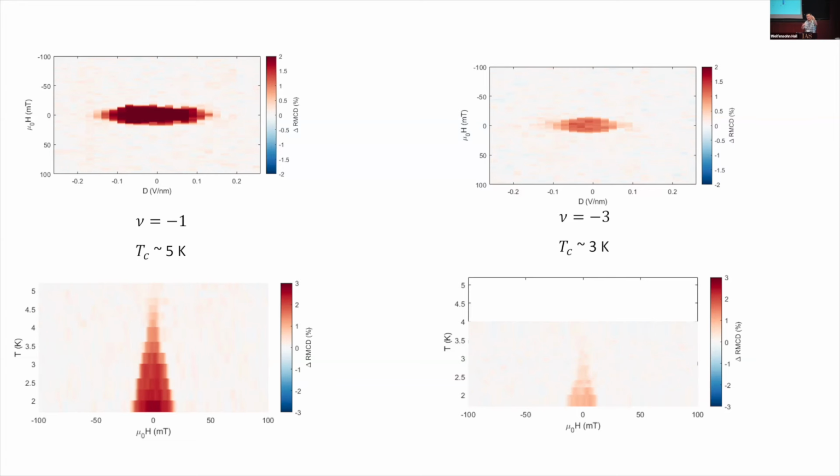When you reduce the twist angle, it means you enlarge the moiré size. Then the absolute carrier density, or you can think of the separation between the carriers in moiré orbitals, becomes larger and larger. Therefore the exchange interaction becomes smaller for smaller twist angles. That's the reason why the Curie temperature reduces as we reduce the twist angle. So everything is consistent. But the take-home message is that we do have ferromagnetism at filling factor -3 for the magic angle of 2.1 degrees.